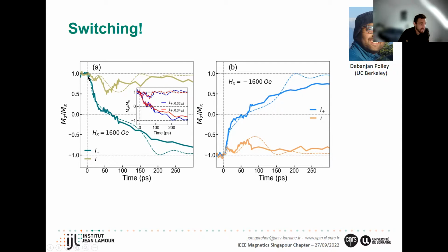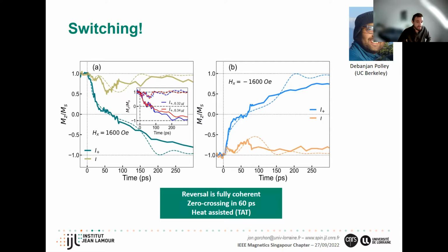And so what we see is that the dynamics are kind of slower than we expected, I would say. It's taking 60 picoseconds to switch, whether we start up or whether we start down. What's actually happening is that we're triggering the dynamics with the picosecond SOT, and then the magnet is just precessing due to the FMR across the equator plane. So this is taking a bit longer. But when we use a macrospin model, which is the dashed line, we actually can get quite a reasonable fitting. And so this would indicate that the switching is purely coherent and not domain wall dominated. So the reversal seems to be fully coherent, zero crossing in 60 picoseconds, and also these thermal anisotropy torques play an important role in this switching.